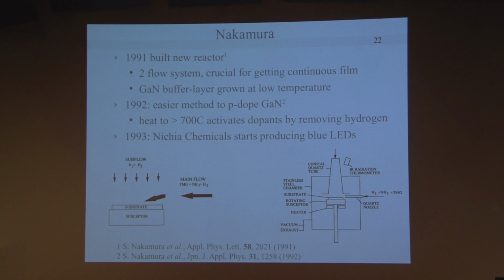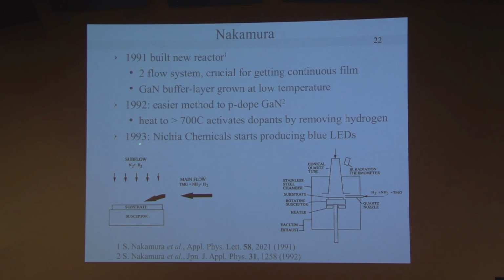And he also found another way of activating the dopants. So again, he used p-type doping of gallium nitride by doping it with magnesium. But he found that if you simply heat up the substrate, this removes the hydrogen that forms a complex with magnesium, and thereby activates the doping. So this activation of the doping that Akasaki and Amano also found was not understood at the time. So he figured out what was actually going on. And 1 year later, so in 1993, Nichia Chemicals, the company where Nakamura worked at the time, started producing blue light-emitting diodes.